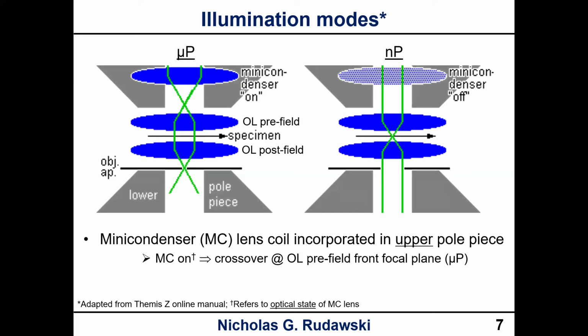If you're in what's called nanoprobe mode, the mini condenser lens is off, and then you don't have the crossover. So then what happens is your beam enters your objective lens pre-field mostly parallel or nearly parallel. Okay, so what you end up with is your beam getting focused to a point on the sample. And it's important to note that when we say on versus off, that doesn't mean that there isn't current going through the coil when it's off. Okay, that specifically means that the lens is optically off.